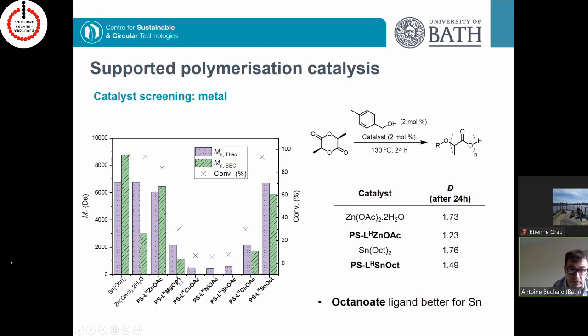And you can see here that from this initial screening, what we could see was that first of all, we had some good activity, which was nice, also some decent dispersities, and also already we could eliminate a couple of metals. And we really quickly focused on zinc and tin itself, actually, even if the first step was trying to remove tin, and I'll show you how in the end we've done that.